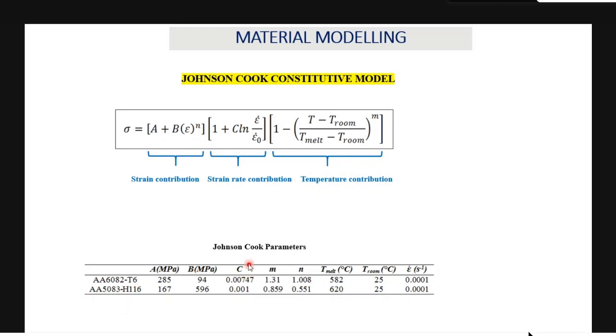Here I showed an example of that, and here C represents the strain rate sensitivity. In Johnson-Cook, they mention it as C, and in some other equations it is mentioned with the letter M. There is some problem with Johnson-Cook when it comes to differences in the strain rate, because in some of the models people are not including the variations of this parameter with the strain rate. If there is a possibility to accommodate the material property with respect to various strain rates, it will give more reliable results, because these values are not constant throughout different strain rates. In friction stir welding, we may have a strain rate from like 100 per second to 1,000. Even some people observed 3,000, 4,000, and so on.